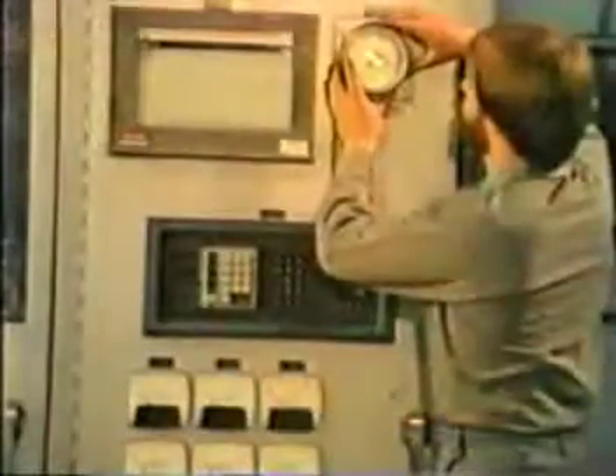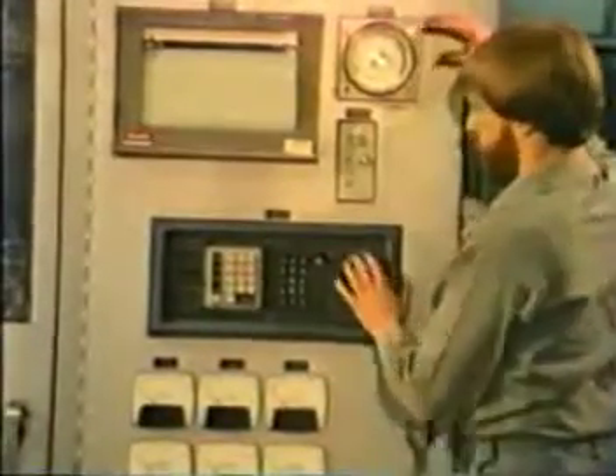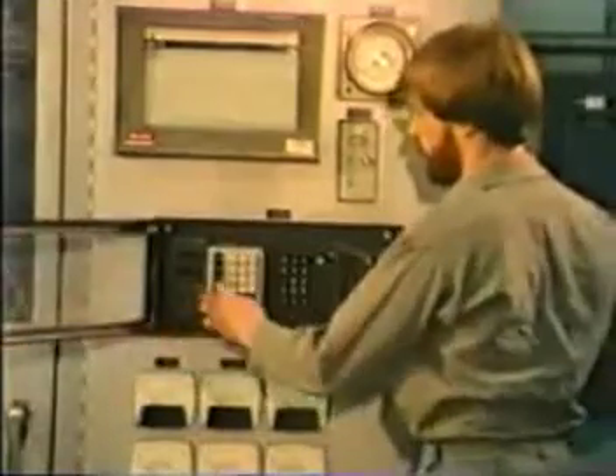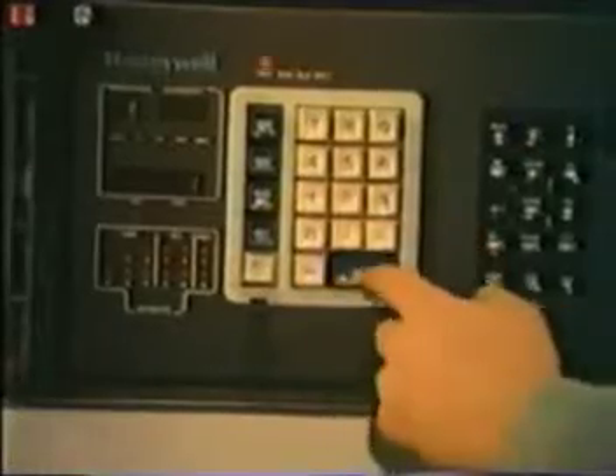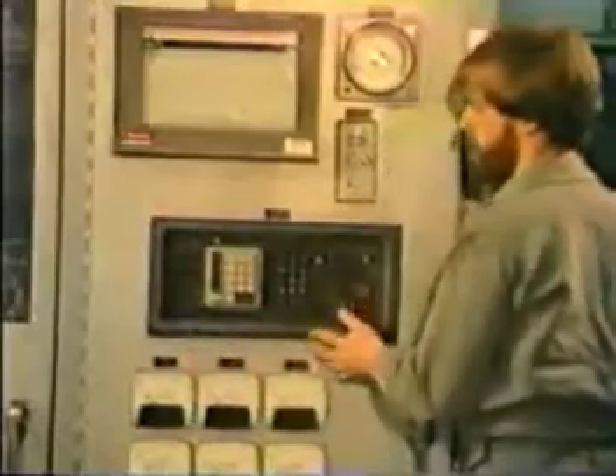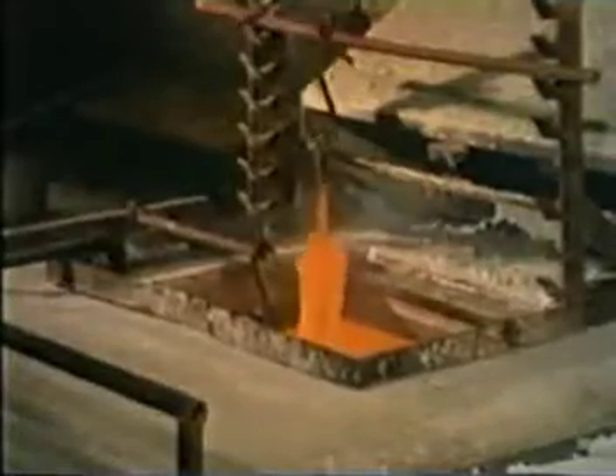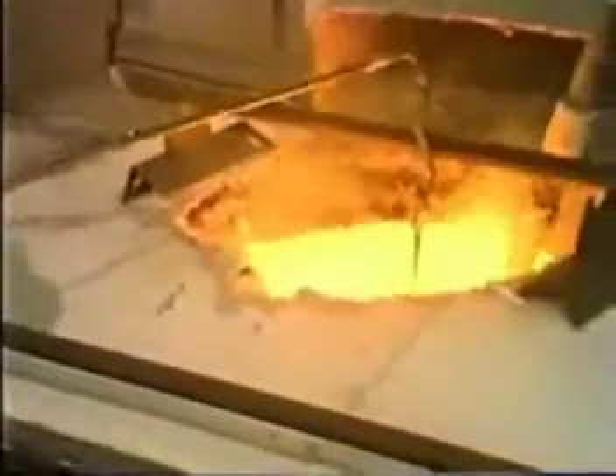The actual temperatures used for hardening alloy steels will range from a low of approximately 1450 degrees Fahrenheit for water hardening tool steel to a high of around 2350 degrees Fahrenheit for high-speed tool steels. To avoid breakage, preheating before hardening is essential when tools such as these high-speed steel drill bits are to be hardened at a temperature of approximately 2200 degrees Fahrenheit.